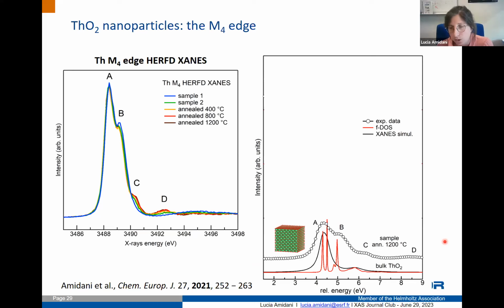Here we are, so in a more delicate case for the F system, but still. The density of states is in red and the spectrum is in black. As you see, there is a problem in the simulation because the second peak doesn't come out in the spectrum, but is present in the density of states. And in the density of states I can see 3 groups of peaks, 1, 2, and the small 3.